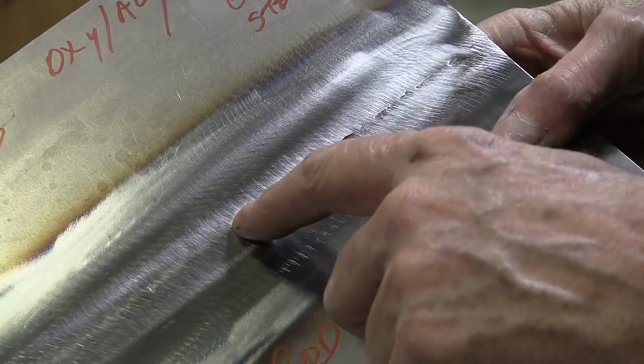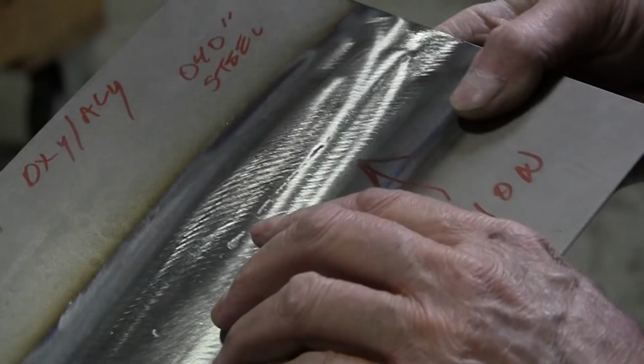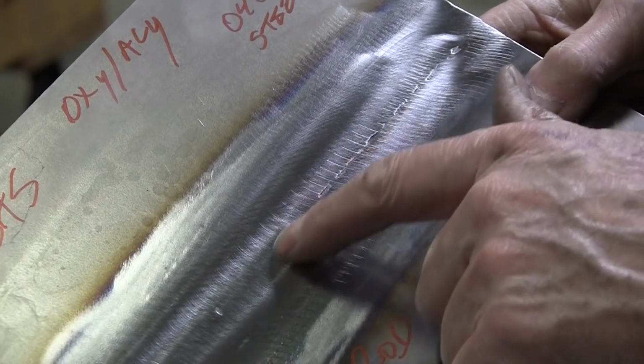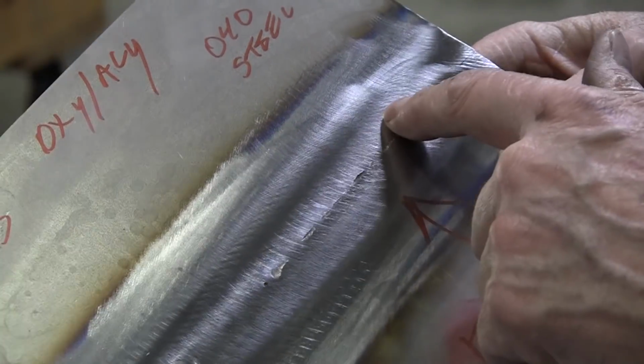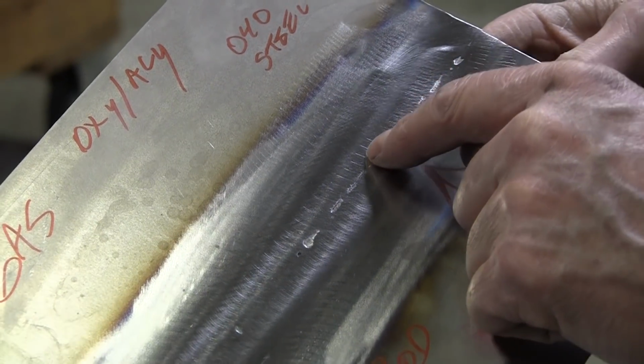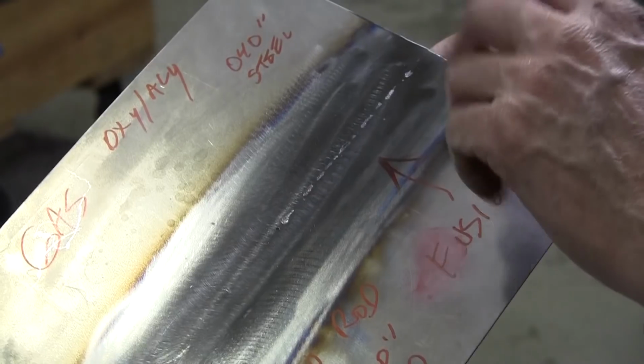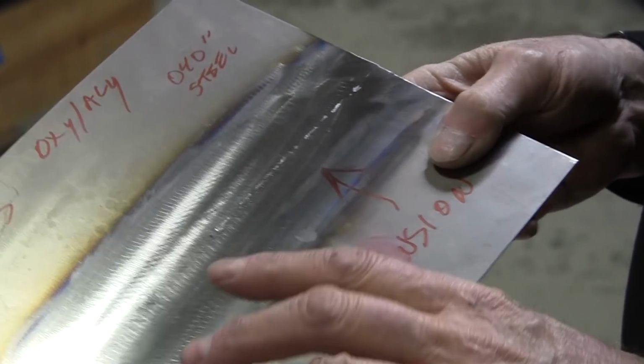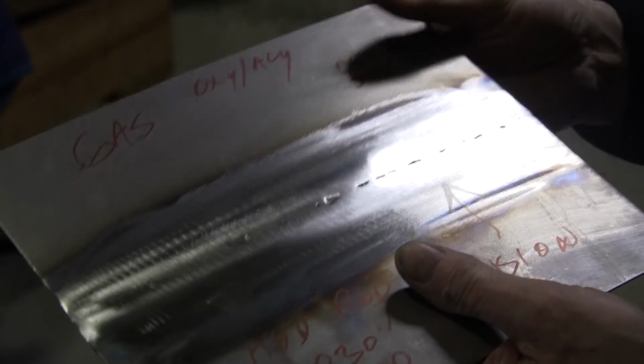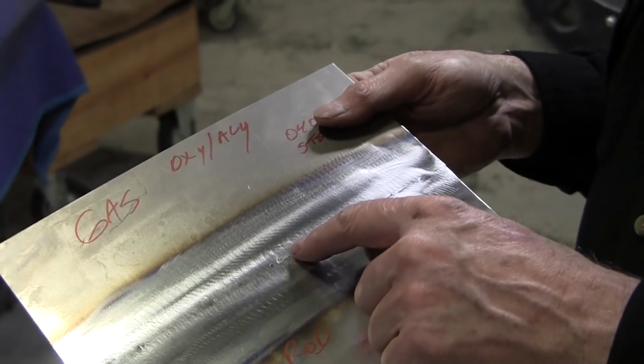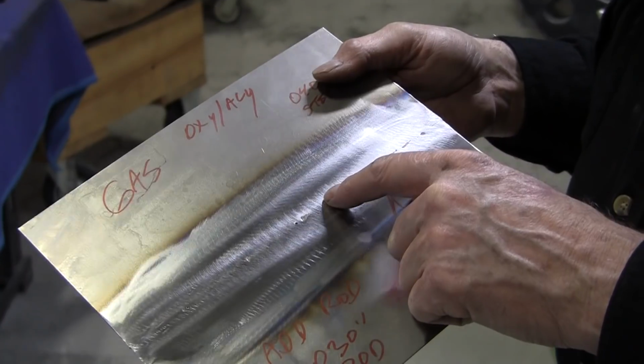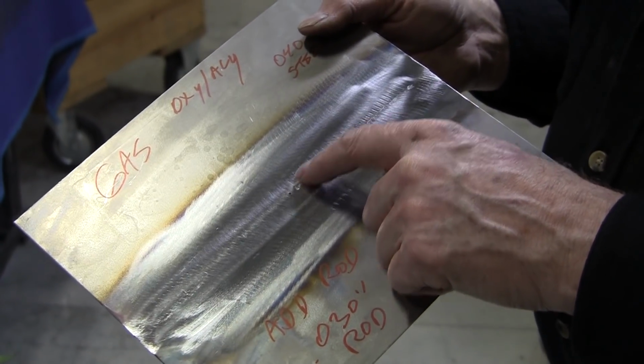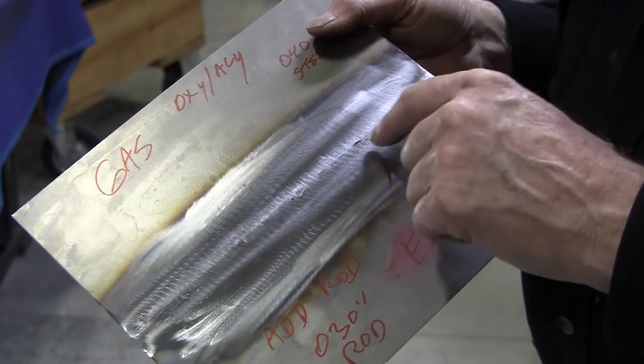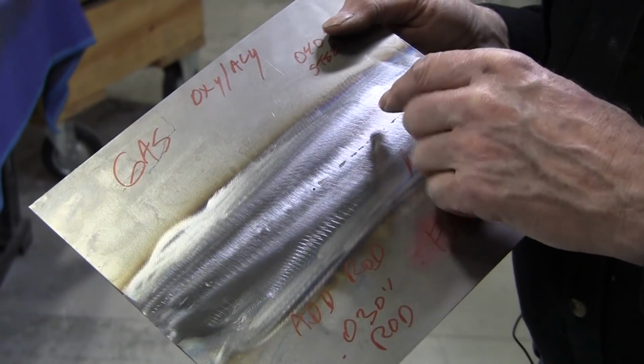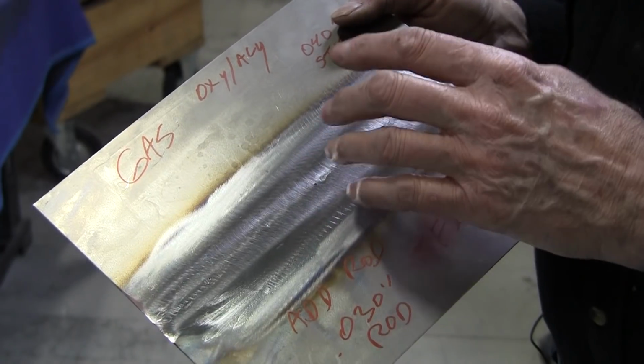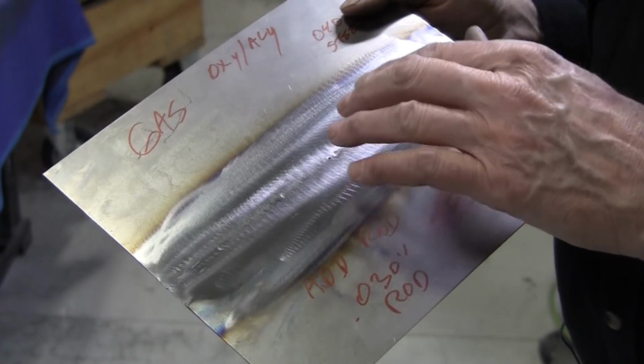And this is where I did the fusion, and there's a considerable undercut here, which I don't like because you're going to have to use fillers on that unless you go in and close up all these undercuts with some more weld, which always leads to a lot more time and is not as successful as you would think sometimes, because it causes a lot more shrinkage and you have to beat it out and everything. So undercuts, if you leave them, they're going to have to be filled with some kind of filler. And all of those in a hot sun environment where the skin of the car can go to 130 degrees easily, those will shrink in.